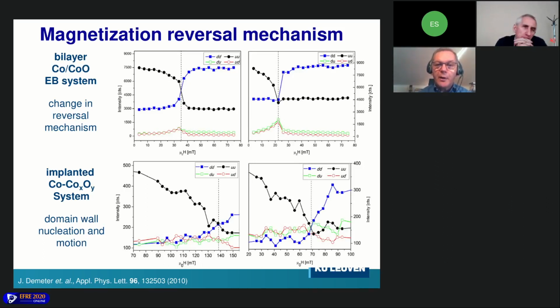The upper part here was well known. This is for the bilayer, where you have a switch in the magnetization reversal mechanism from domain wall nucleation to rotation. In our implanted system, we see that it is always domain wall nucleation and motion. So we have modified the system in such a way that the rotation of magnetization is no longer occurring.